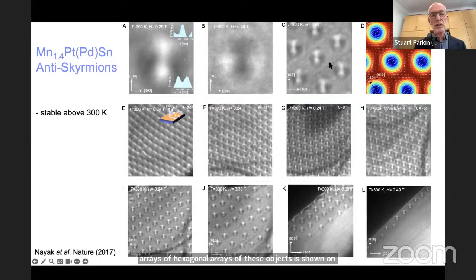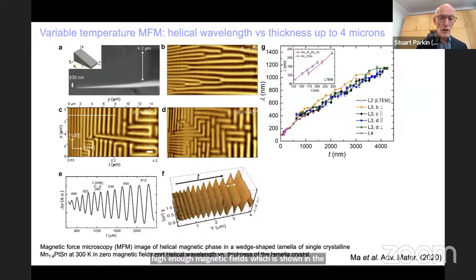And then as we further increase the magnetic field, out of the plane of this lamella, you can see that there's not much change in the array of the antiskyrmions, except eventually they will disappear at high enough magnetic fields, which is shown in the bottom right, with just a single chain of antiskyrmions along the edge of the lamella. We can use a different technique for imaging these objects.